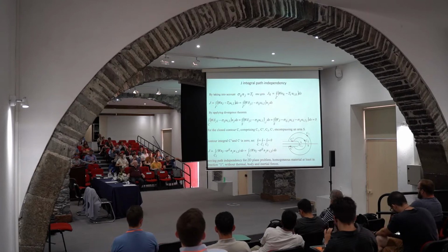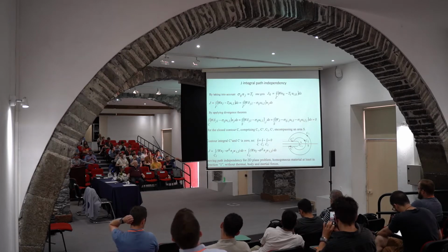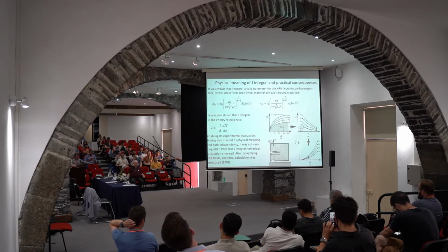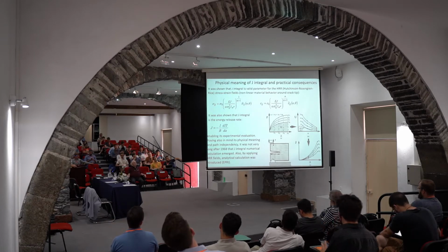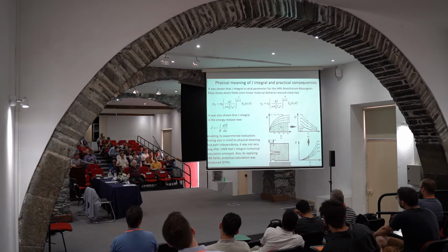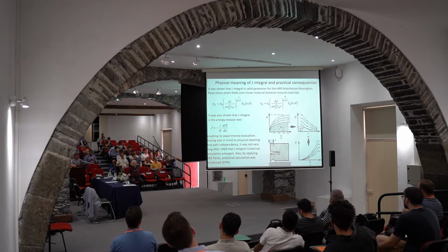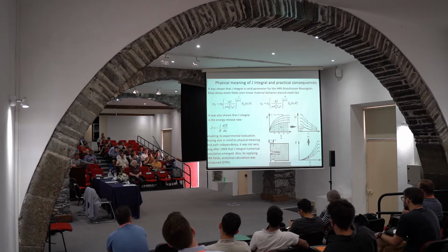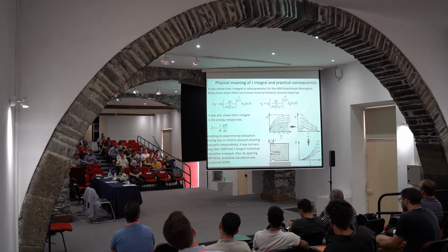And that also enables physical interpretation as energy release rate, as you can see here. And finally, just to remind you that elastic crack tip fields are characterized by J, as you can see in these equations correlating stress and strain with their fields. So the first actual measurement was based on these sketches shown here.